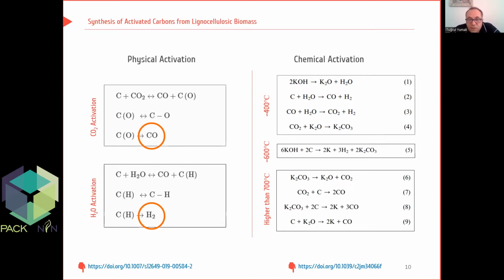The oxygen added into the system is also partially chemisorbed on the surface, generating oxygen-containing surface functional groups. Carbon dioxide and steam generate different pore size distributions due to the site-produced inhibitors. The inhibitors are carbon monoxide in carbon dioxide activation and hydrogen in steam activation. This enhances the microporosity during carbon dioxide activation and mesoporosity during steam activation, with the consequent formation of different functional groups, but they are both oxygen-containing functional groups.